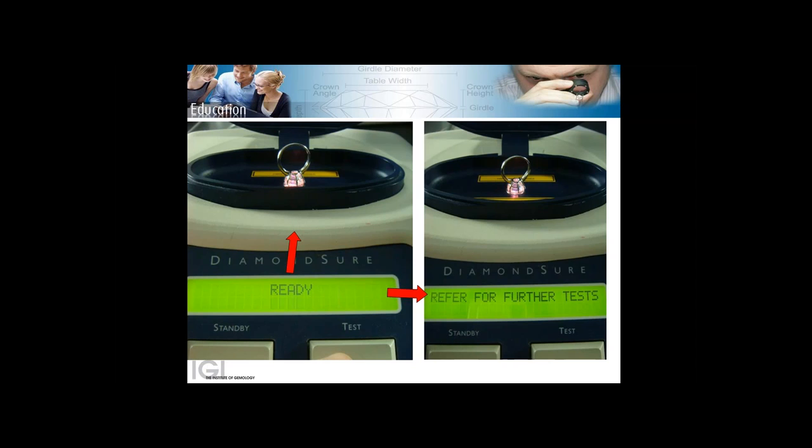So it becomes very important when you're sourcing diamonds that you know where you're getting these diamonds from. Is it from the right source? Now, talking also about the sizes, what you need to watch out for are sizes which are 30 points plus. That's mostly where we see more and more CVD coming in. 20 points, rarely. Below 20 points, almost negligible. Very rarely have we seen stones which are 15 or 18 points. But mostly 20 points, and 30 points and above is something which is more and more common to see in CVD.